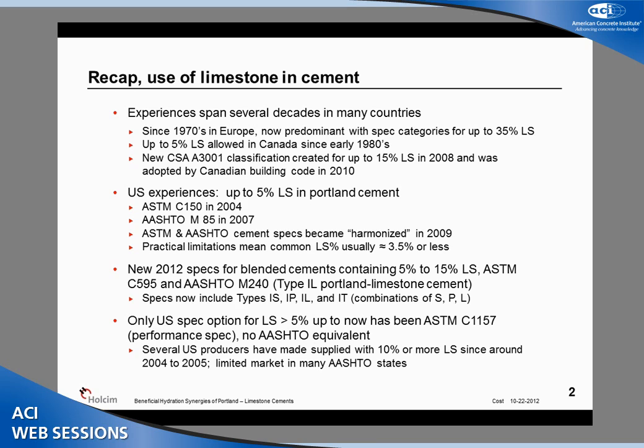Just as a brief recap, we have quite a bit of experience with Portland limestone cements around the world, over many years. In the U.S., we have really just in the last 8 years or so seen a minor proportion of limestone allowed in ordinary Portland cement. And then the recent specification changes that I mentioned are common both to ASTM and to AASHTO, allowing a 5 to 15% limestone amount in a blended cement category.